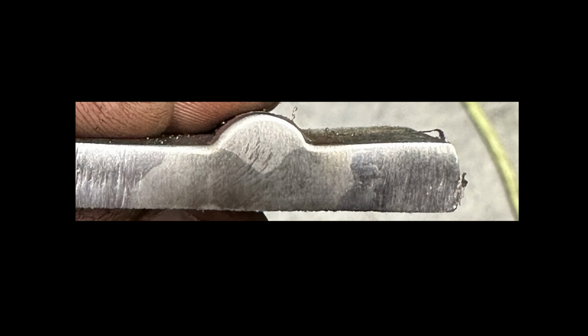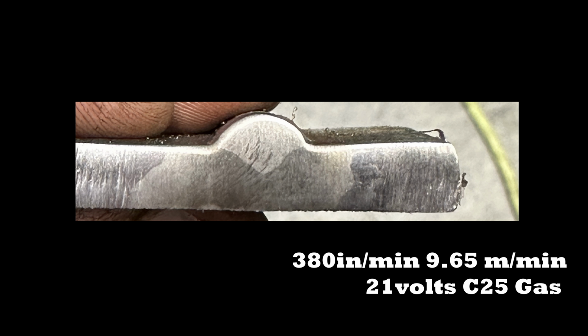So here's a test plate, quarter inch thick. This was a pulled short arc, short circuit MIG. The penetration is actually pretty decent on this flat plate, which realistically is pretty easy to get on a flat plate. The bead is a little bit crowned up because it was pulled. It'd be flatter if it was pushed, but this is pretty much the end of the road for the short arc process. It's not going to get much better than this.